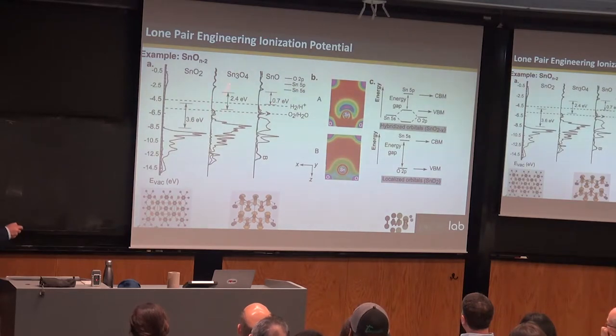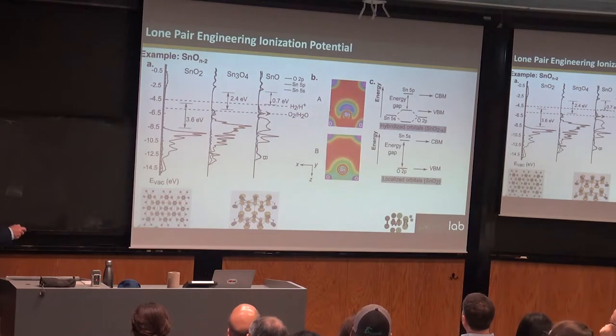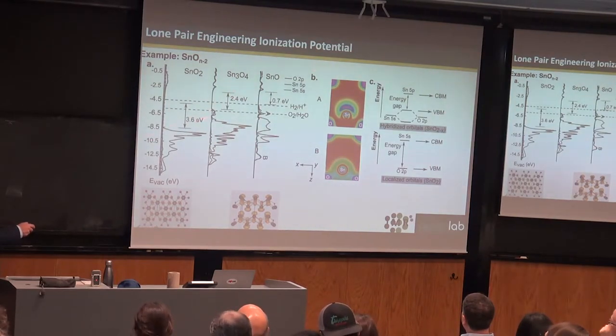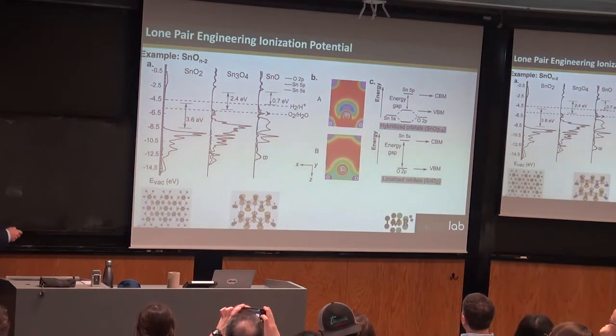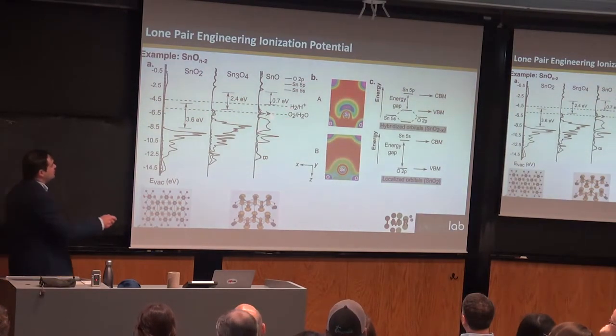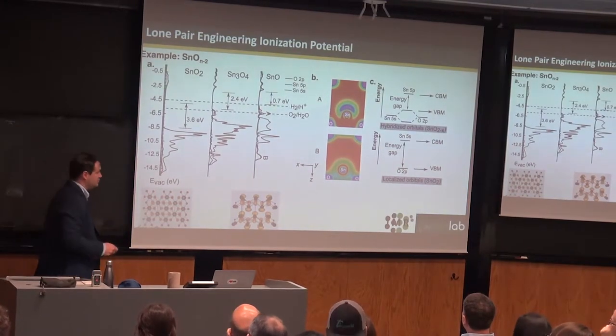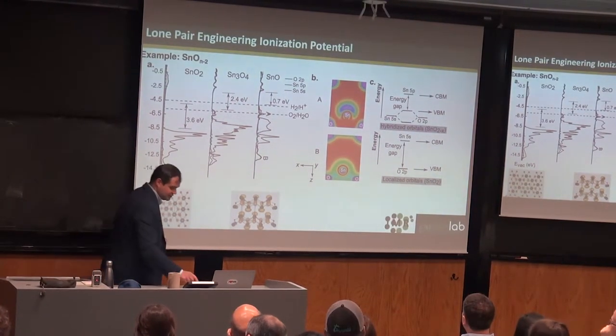This sort of band gap is more preferable, and this ability to tune these lone pair states in order to raise your valence band maximum or ionization potential in such a way that we could engineer good alignment with the redox potential, specifically the water oxidation.